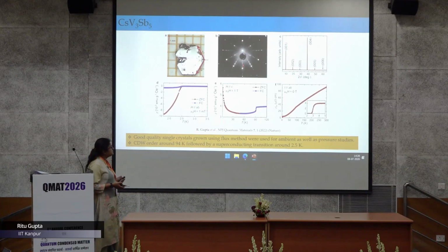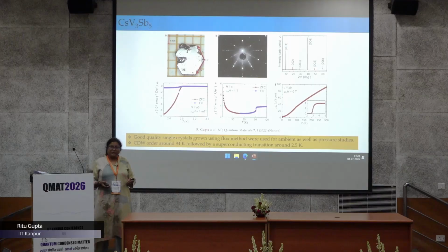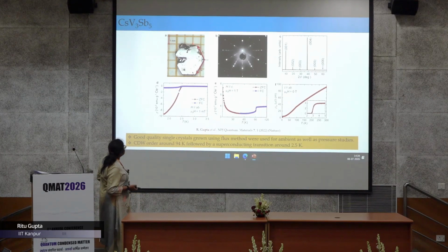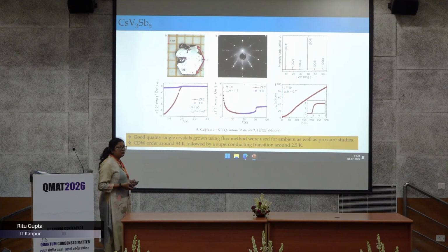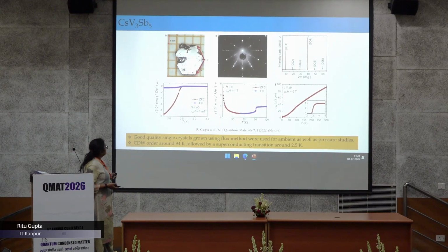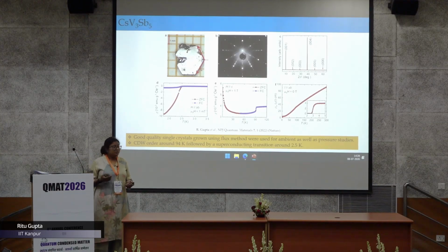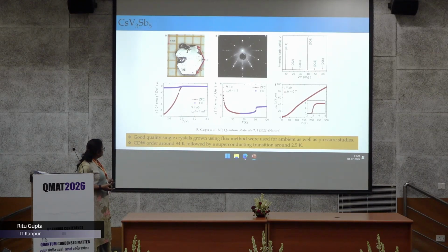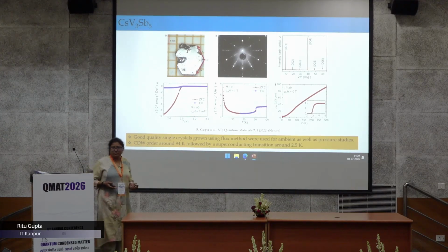These are the crystals which we used for MUSR studies at ambient pressure as well as under pressure. In the optical picture, these were grown using the flux method, and you can see a very beautiful hexagonal symmetry of this crystal, visible in the optical picture itself. Then the Laue pattern shows the hexagonal symmetry, and the XRD shows that the crystals are grown along the C-axis. In the magnetic susceptibility you can see a drop around 94 Kelvin, and a kink in resistivity, which is because of the charge order formation.